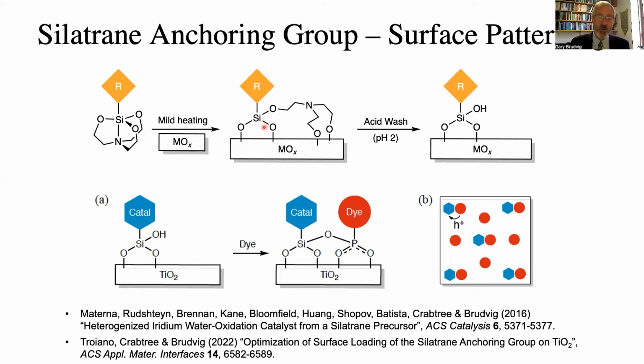This linkage is stable over a pH range from 2 to 11. And it's also both oxidatively stable and reductively stable. And so this has been really significant. It's much more effective than just the siloxane itself, which is very difficult to handle synthetically and also is very challenging to put down on a surface in a well-defined way because it polymerizes so readily.